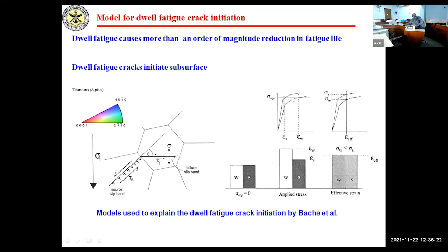Now, if I take a stress strain curve and try to explain this phenomenon, it is like this. You have the hard oriented region and this region which has lower stress requirement, and then there can be two cases. One is iso stress condition and one is iso strain condition. If you take an iso stress condition, the weak grain deforms more as compared to the strong grain. So there is a strain incompatibility which comes in. If you have iso strain condition, the weak grain deforms and the strong grain deforms. So what happens is, when you apply this stress, the weak grain deforms and basically unloads onto the strong grains, and this is what is called load shedding or unloading, and it causes cracking in the hard oriented region. I will show you this.